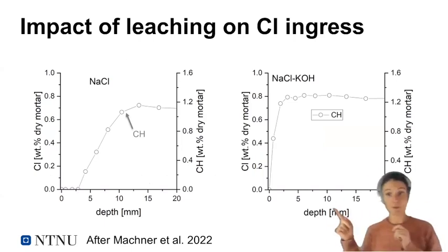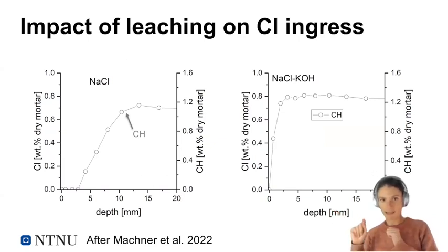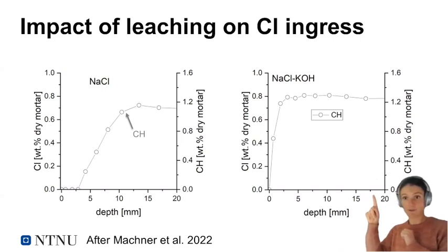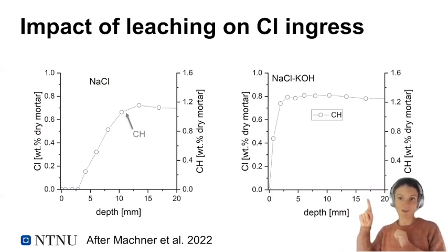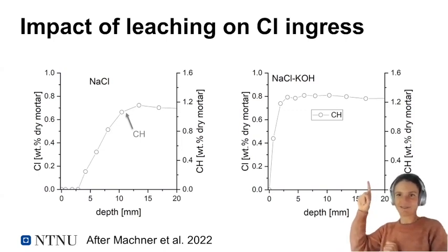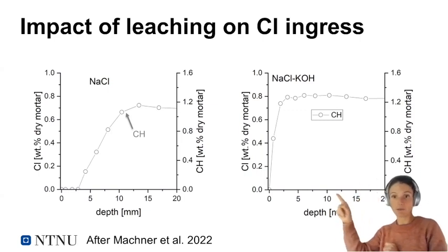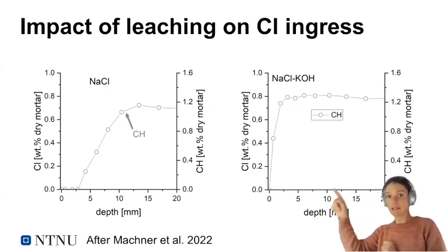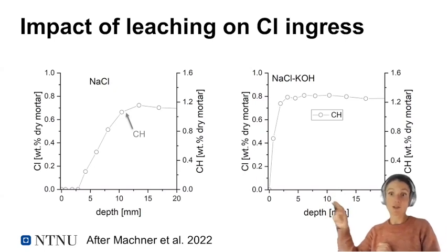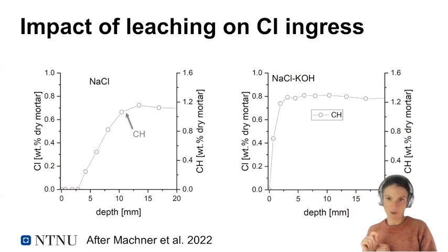So on the left, we have sodium chloride. On the horizontal axis, we can see that the Portlandite content starts to decrease from a value of about 10 millimeters in. That's for the sodium chloride exposure. If we look at this graph here, where we have added potassium hydroxide to limit leaching, we can see that the Portlandite is actually on a background level, and it's only decreasing in the outer couple of millimeters. So we are able to limit leaching by adding potassium hydroxide.